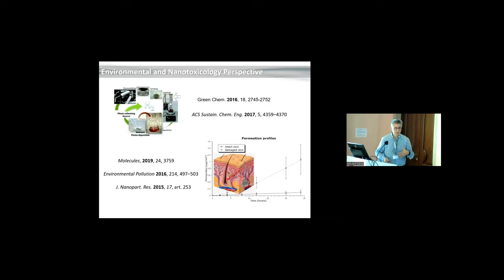Saying that, we have to look at the composition of our catalysts, we have to reduce the content of noble metals. I have to mention that a way is also to recycle catalysts. So we have car converters containing grams of platinum, palladium that are designed to be stable, so it's difficult to extract them. We have been working also on alternative ways to recover those metals and reuse them for making more efficient catalysts, like the process, also patents we have, on recovering palladium. And of course, working with nanomaterials, it is also important to underline aspects related to toxicology, nanotoxicology. So we are also involved in experiments of skin permeation of platinum, cerium, titanium nanoparticles, and so on and so forth. So this is an important message for young people.